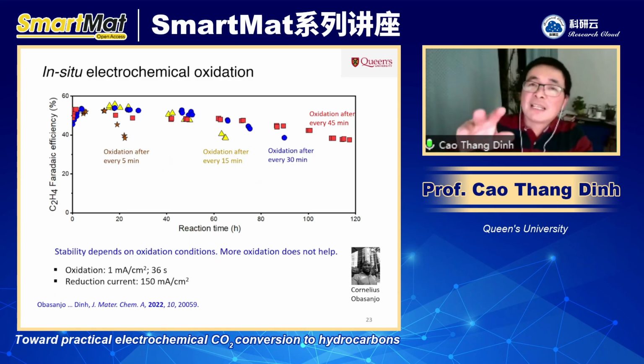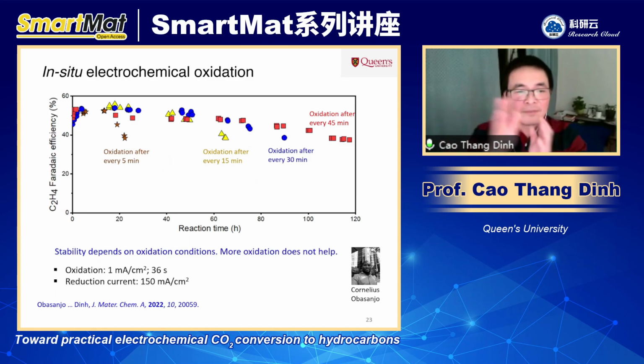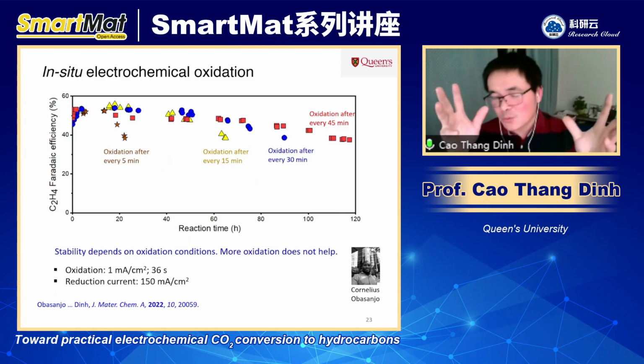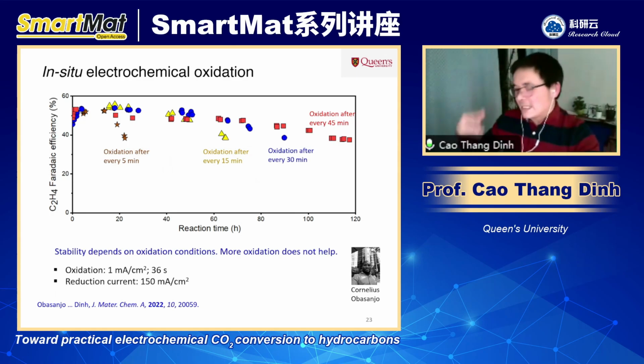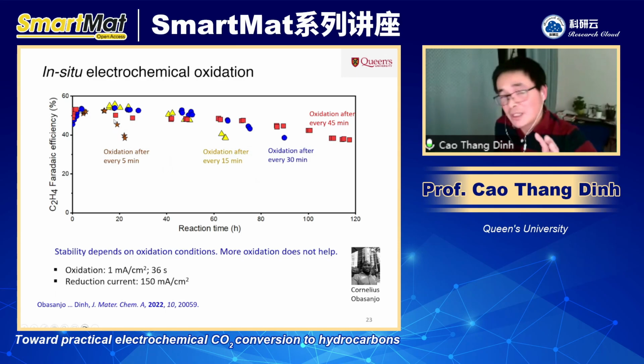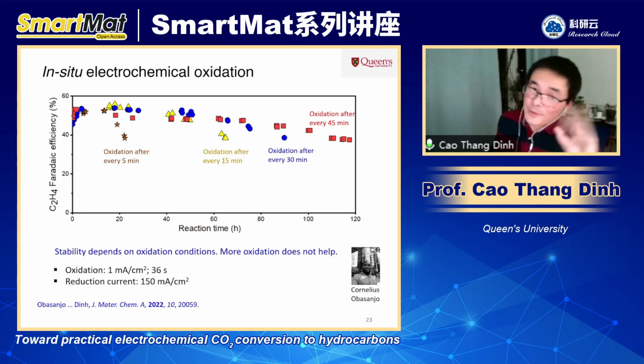So we run the reaction and then after a certain time, let's say after 5 minutes, we oxidize, or maybe after 15 minutes, we oxidize, or after 30 minutes, we oxidize. And then we see how we can extend the reaction time. So in this graph, we track the Faraday efficiency of ethylene. Right? Without doing anything, we know that it's stable for only 4 or 5 hours, from the previous slides. But now if you do the oxidation every 5 minutes, you can extend the lifetime to about 20 hours, which is a little bit better, already 4 times.